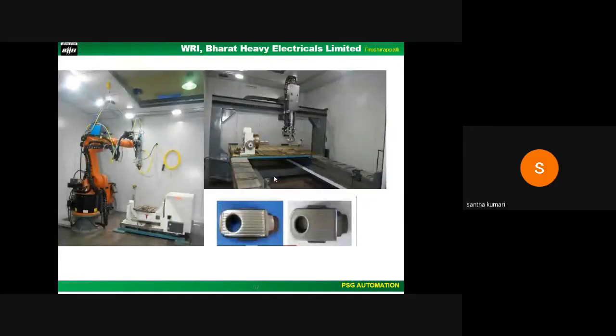WRI has the state-of-the-art facility with a high quality fiber laser. We have multiple processing heads for cladding, external and internal cladding, and also welding, and CNC and robot processing stations. A 6 kilowatt fiber laser with a dual beam in a time sharing mode is being used. Laser can be transported to either the CNC or a robot station. We have a 1800 length, 2500 width and 800 height 6-axis robot coupled with a 2-axis turn and tilt. The robot has 30 kg capacity and can be used for cladding.